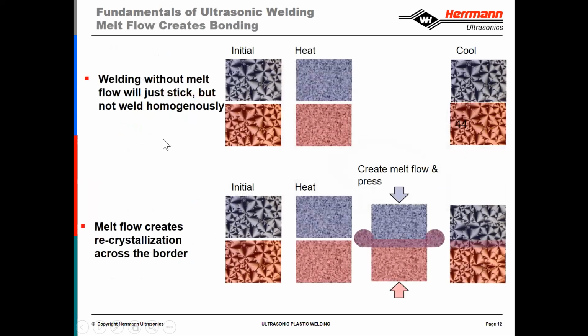So it's important for us to get the right amount of heat into the plastic parts. If we don't have enough heat, we may still melt the energy director, and the parts may stick, but there's really not a homogeneous weld. Initially, the crystallized solid part, as you heat it up, those molecules start to move around, get excited, the polymer chains break, and if they cool, and we haven't reached the melting temperature of the materials again, you might get some sticking of the parts together, but there's not a true homogeneous mixing of the melt.